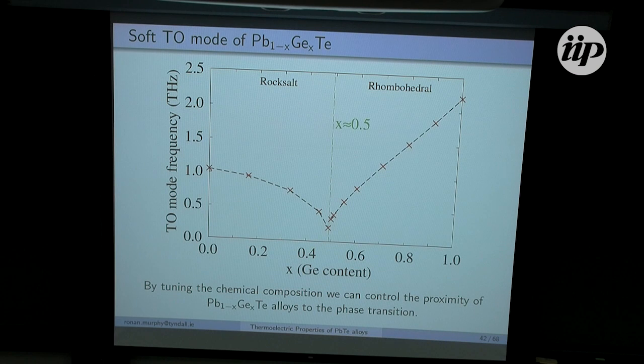So this just shows that although our interatomic force constants are temperature independent, we do still capture this phase transition as a function of alloy composition. And by simply varying that, we can control the proximity of these lead germanium telluride alloys to the phase transition.